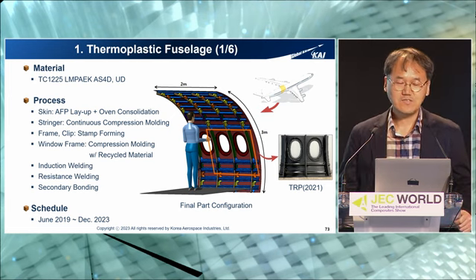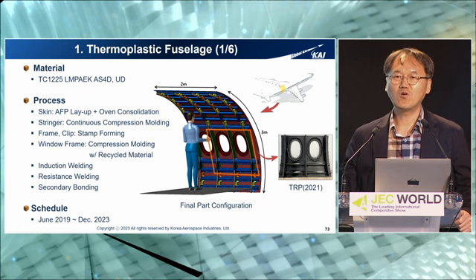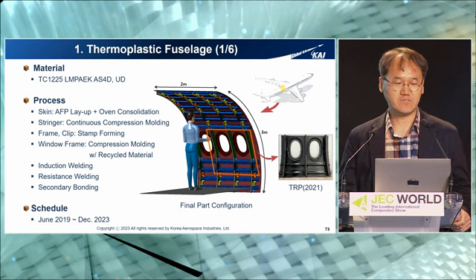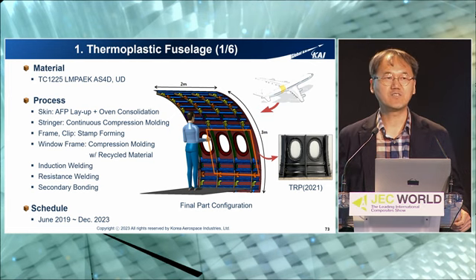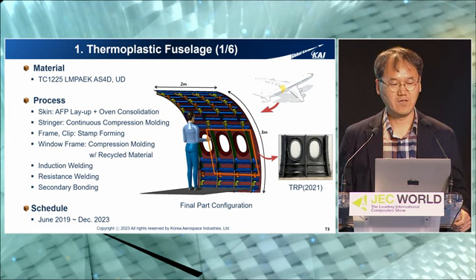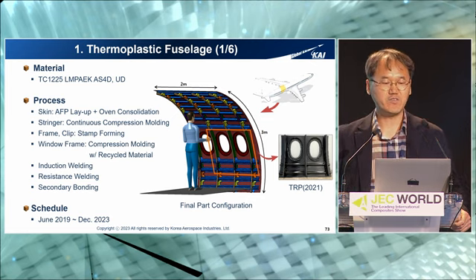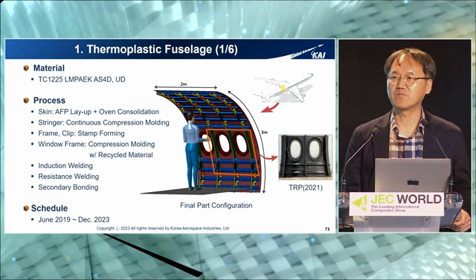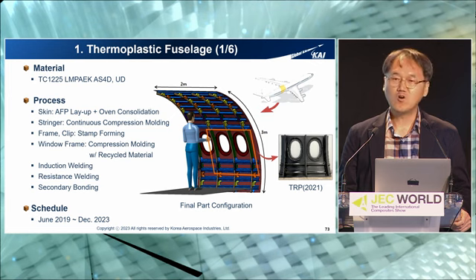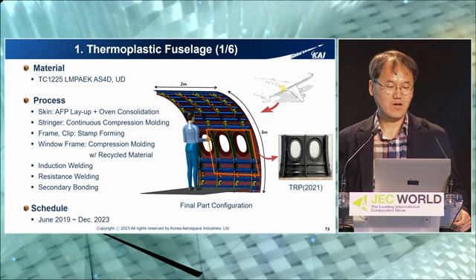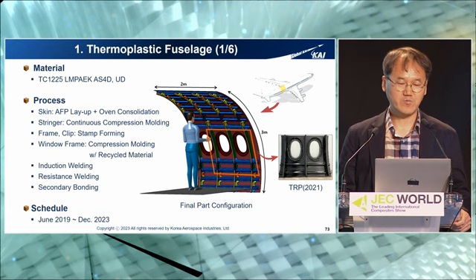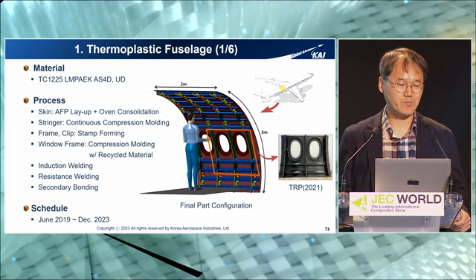For the thermoplastic technology, KAI wants to implement the whole fuselage structure with thermoplastic materials. We selected LMPAEK material with a unidirectional tape. For the large skin, we selected an AFP machine to lay up the large curved skin and oven consolidation, not autoclave consolidation. For a long stringer, we selected the continuous compression molding process, and for relatively smaller parts, such as frames and clips, we applied the stamping process.